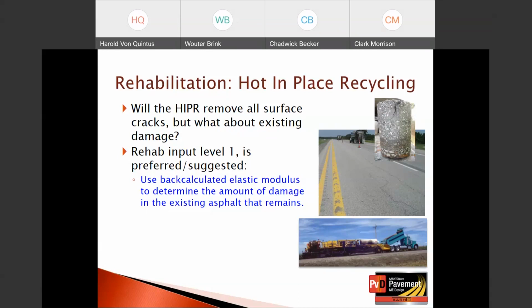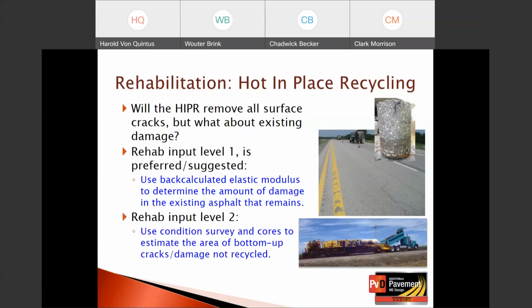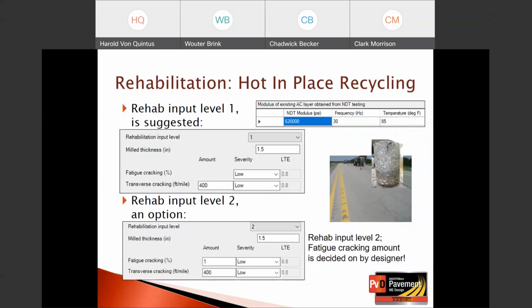So what we see on the surface would be entered for rehab 2, even for a hot in place recycling, the amount of bottom up cracking prior to overlay, after the hot in place recycled material is completed. Rehab level 2 uses the condition survey and cores to estimate area of bottom up cracks and damage that's not recycled. Kind of just what I previously said.